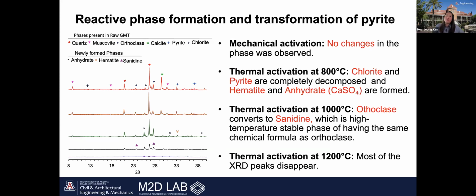So after the activation, we first looked at the XRD results to see how the phases changed. After the mechanical activation, there was no significant change. As you can see, the material stayed mostly crystalline. However, at 800 degrees Celsius, with thermal activation, we saw major changes. Pyrite and chlorite broke down completely, and new phases like hematite and anhydrite formed. And this shows the start of higher reactivity. At 1000 degrees Celsius, orthoclase changed into sanidine, meaning the structure was rearranged by heat. And at 1200 degrees Celsius, most crystalline peaks disappeared, meaning the material became mostly amorphous and more reactive.